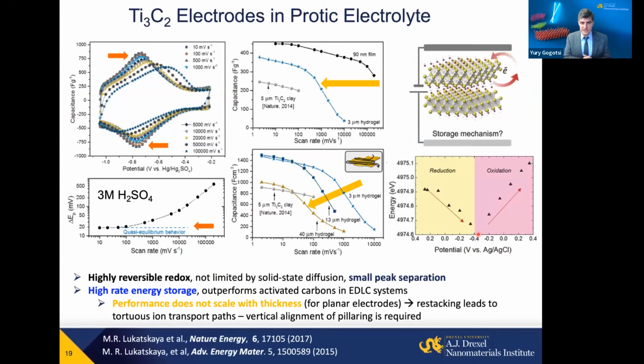But if we know all this, how basically ions and solvent molecules behave, we also need to understand whether we can really have fast redox storage. And the good thing, the answer is yes. First, we can have redox. You can see from X-ray absorption spectroscopy that the oxidation state of titanium atoms in titanium carbide MXene in protic electrolyte like sulfuric acid changes. This is a typical electrolyte being used especially for fundamental studies, but also in your lead acid batteries in cars here. There is a change in redox state, so it means that we have charge transfer.